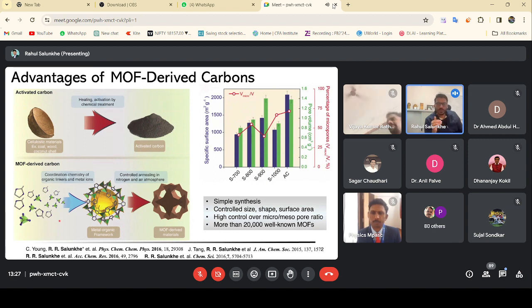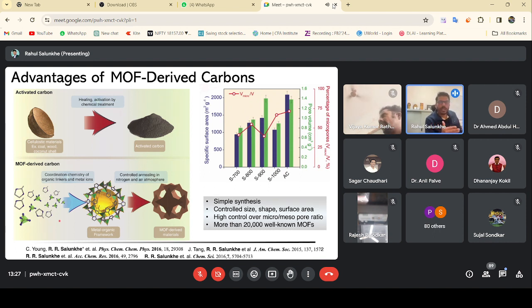And because they can achieve a very high surface area, they are very fascinating for various application fields like sensors, solar cells, batteries, supercapacitors, catalysis, or any other application you can take. As we can see, based upon our synthesis method, we can control the surface area and pore size distribution. The temperature we optimize for this material will decide the surface area and the pore structure.